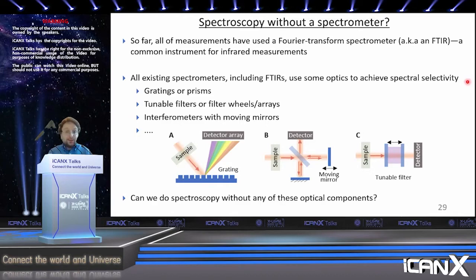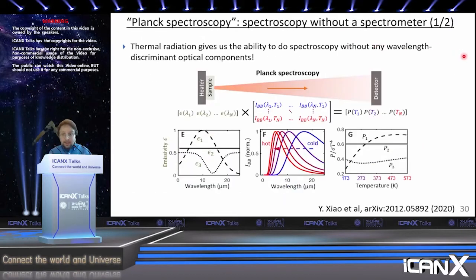And what I'm going to show you is that thermal radiation can be used to build a spectroscopy technique that doesn't have any optical components that actually give you the spectral selectivity. You don't need any of them. And so this is a compelling concept of doing spectroscopy really without having a spectrometer. So the way that we do this is a technique that we call Planck spectroscopy. Essentially, thermal radiation gives us the ability to do spectroscopy without any wavelength discriminating optical components. And the basic setup, the most simple version of this, is exceedingly simple. You take a sample, you put it on a heat stage, and you have a detector over here, and you're measuring the thermal radiation as a function of temperature on the heat stage, and that's all you need to do in terms of a measurement, and you can recover the relevant spectra of the sample and of the light that's being emitted by the sample.